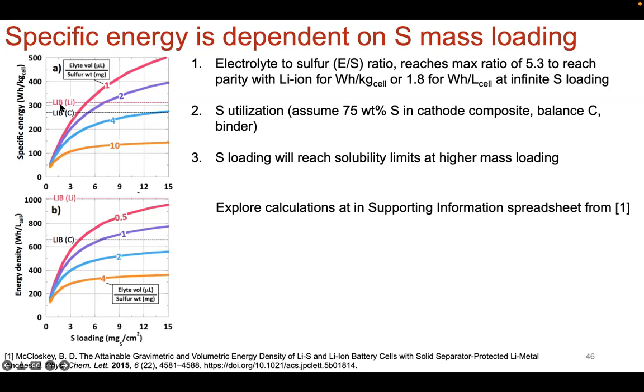So in terms of competing with lithium metal batteries or lithium ion batteries with graphite anode, what we're really looking at here is, in terms of sulfur mass loading, something between like 9 and 10 milligrams per centimeter squared. If you don't have a feel for how much sulfur that is, it's an extremely high mass loading. And on top of that, if you're at that high of a regime, you now are running into solubility issues in terms of mass loading for sulfur. So it's quite a balance. If you want to achieve higher specific energy, yes, you use less electrolyte, but is that going to contribute to capacity fade in the performance of the battery, just because there isn't enough electrolyte there to actually run the battery?